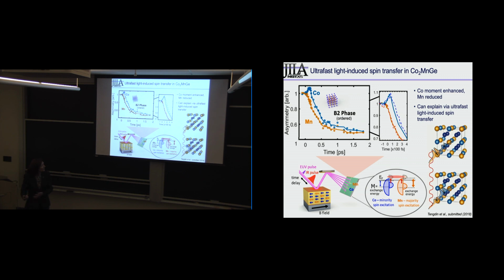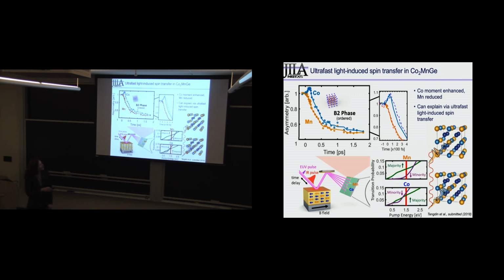So with our collaborators, Ole Eriksson's group from Uppsala, Ole calculated that if you integrate over all the transitions, it is more likely to excite a minority spin in cobalt and a majority spin in manganese. And so that means that the light is effectively transferring the spin polarization. If you integrate over all possible transition probabilities, at the laser photon energy we're using, it's easier to excite the minority band in cobalt and the majority band in manganese, and that essentially takes spin polarization from the manganese to the cobalt.